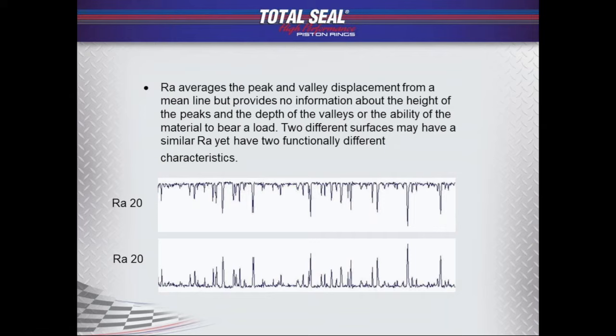The upper surface, as you can see, has a beautiful plateau right across the top. Great low profile surface. And the surface down at the bottom, which is completely inverted, has nothing but peaks, no valleys. And using Ra, they're measuring the same. Using just a simple pocket surf or something like that will only measure Ra, you can have a great surface finish number, but have an effectively horrible surface finish. So that's why we don't use Ra.